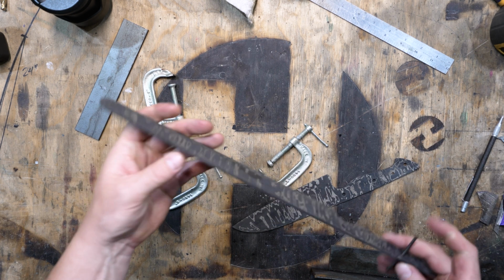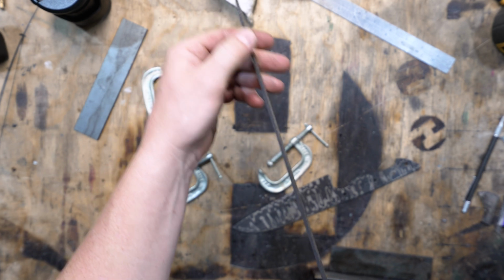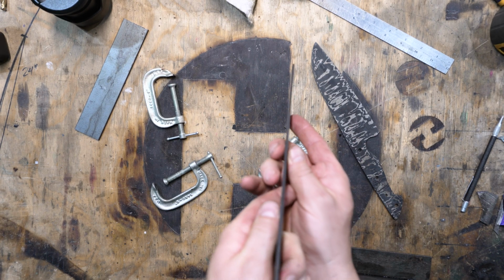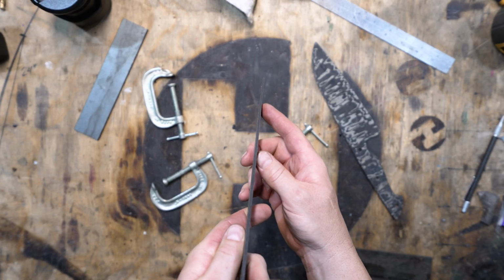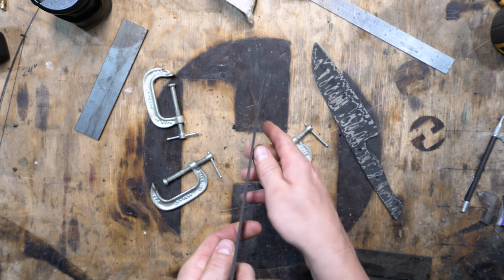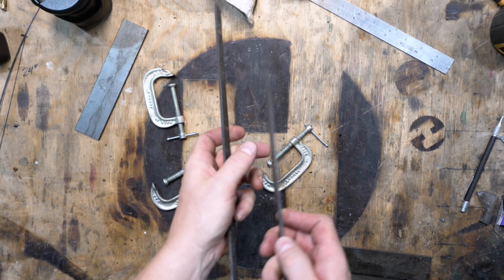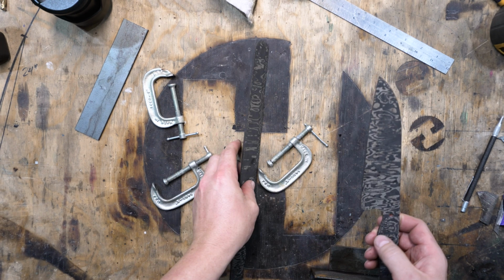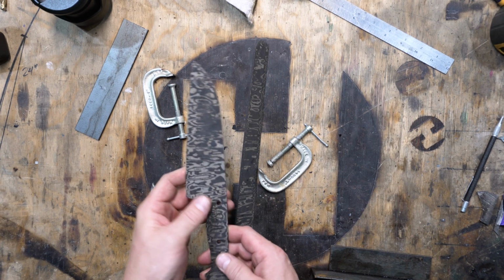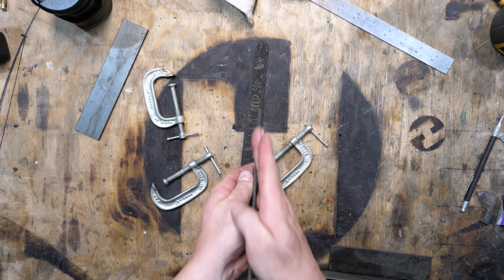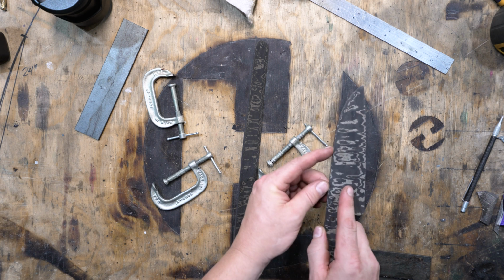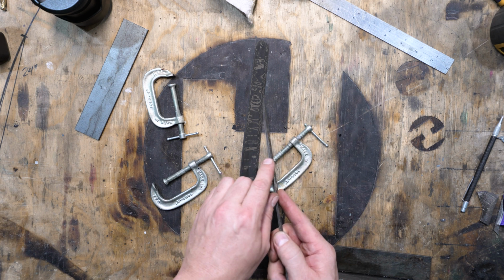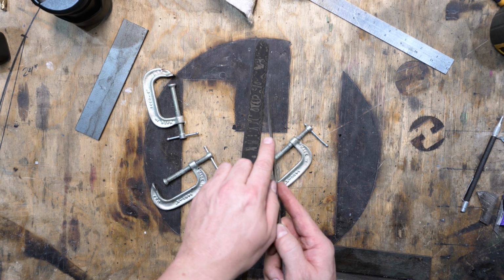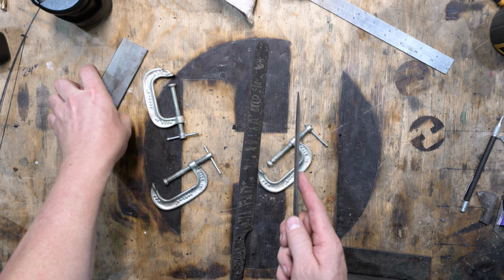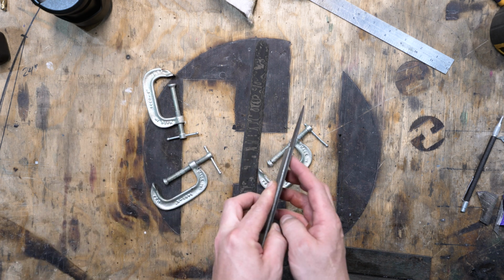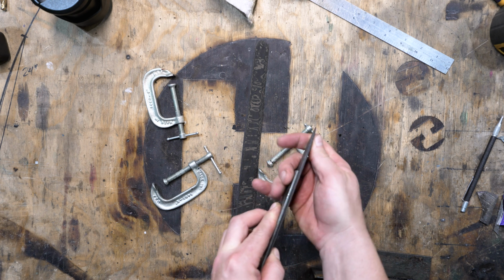The first temper cycle is done. Now I need to address the warps in these two knives, and they're really straight except for right up here toward the front, and they have like a nice little bow in them, just a little too much to grind out. So what I do is I'm going to take this, so this one's bowing this direction, so I'm going to lay this on a flat surface and look at it from the side, and wherever I see this start to lift up off of the flat surface, I'm going to mark it. That way I know to put the mark even with my piece that's going to raise it up, so I can bow this in.